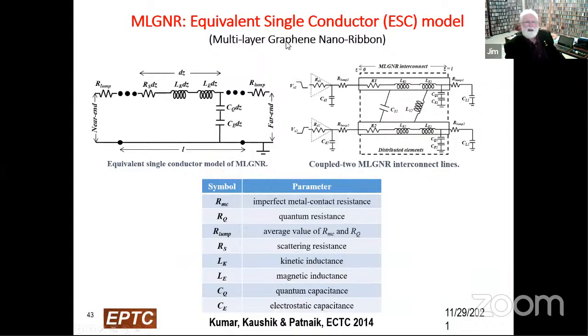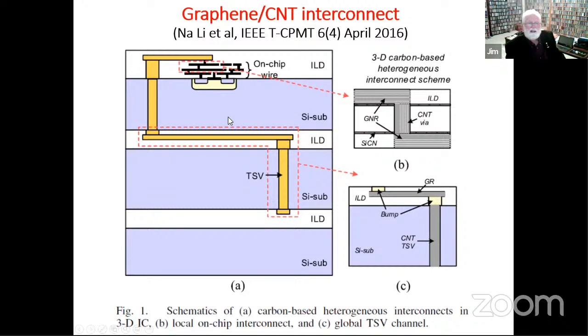You can have graphene conductors, multi-layer graphene nanoribbon. The models are just like a regular transmission line model for crosstalk and so on. But the idea is if you can have graphene interconnect laterally and through silicon via carbon nanotubes, then you've got a carbon transmission system here. And so this is an idea that people are trying, to make contacts from the graphene to the carbon nanotubes.